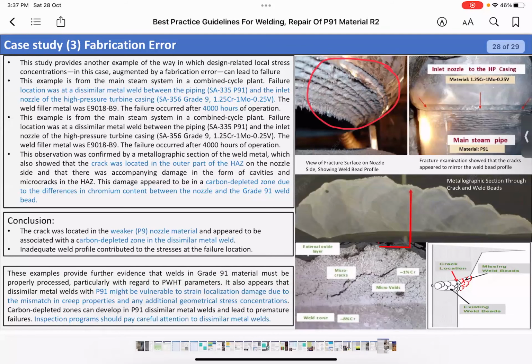The failure occurred after 4,000 hours of operation, and the crack was located in the outer part of the heat-affected zone on the nozzle side. As we see here, there were missing weld beads. This has contributed to the early failure in this weld configuration.